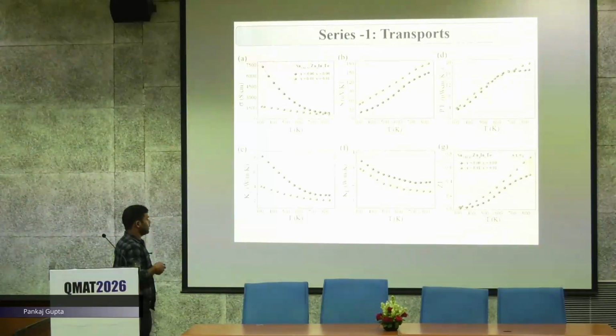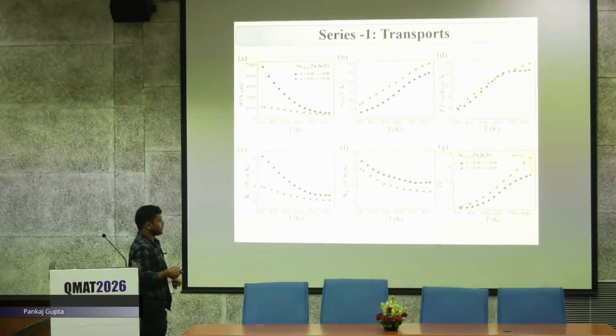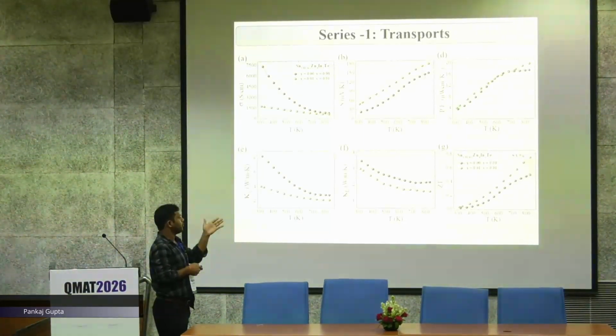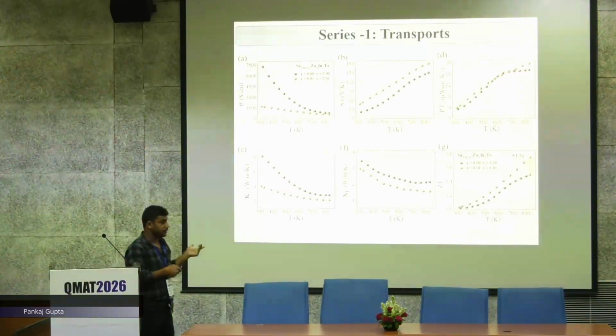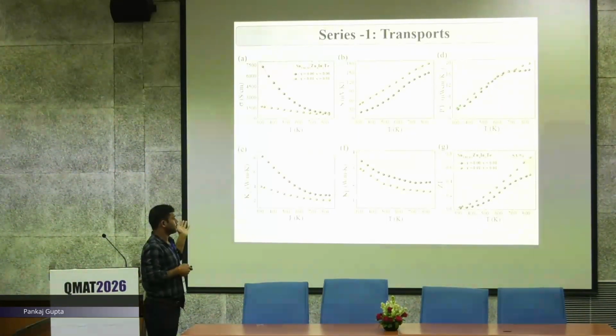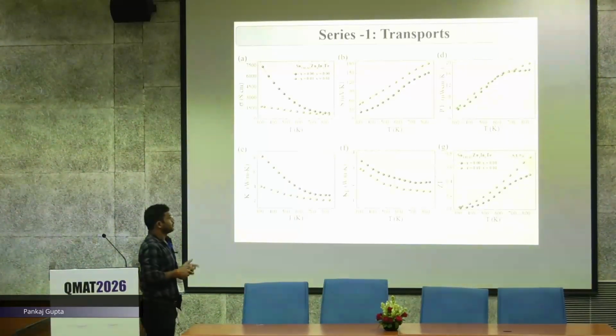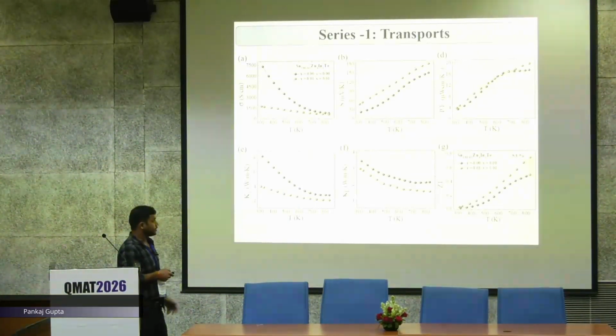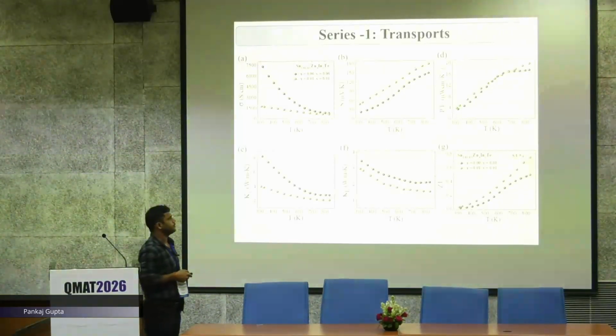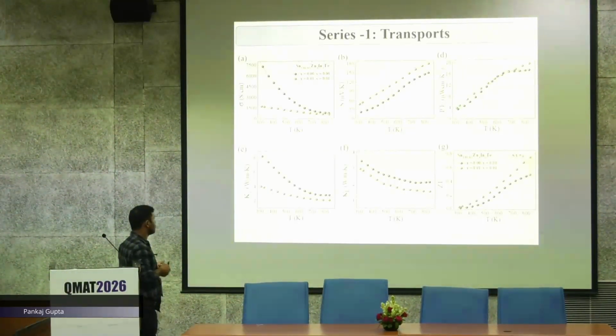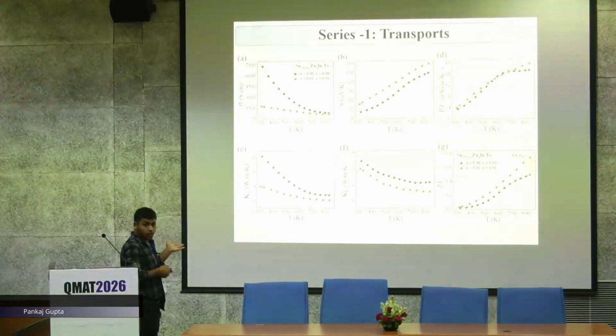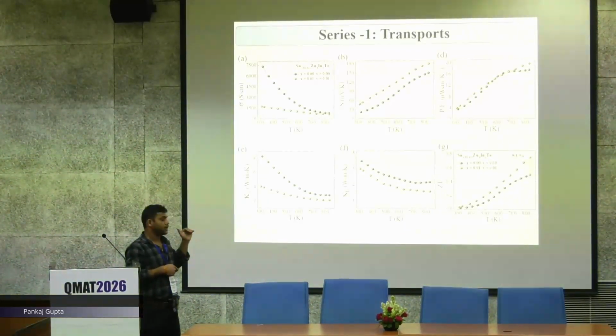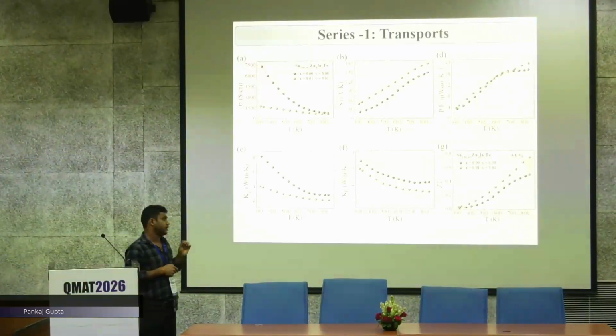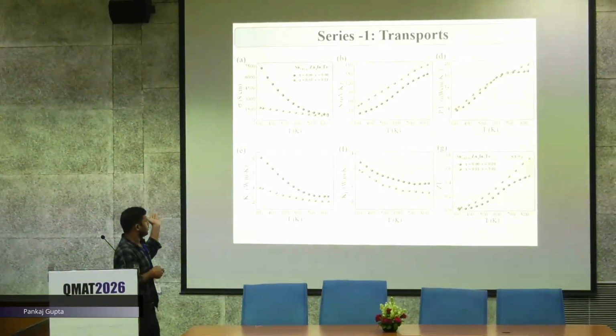At the same time, thermal conductivity is very low because electrical thermal conductivity also depends on the electrical conductivity, and also disorder is there. We extracted the lattice thermal conductivity by using the Wiedemann-Franz law, that is the total thermal conductivity minus the electronic thermal conductivity, and in this way we could increase the zT figure of merit by 53%, but still there is a lot of scope to reduce this thermal conductivity, because the theoretical minimum value of thermal conductivity is reported to be 0.4 watt per meter Kelvin. So we thought to reduce it further.